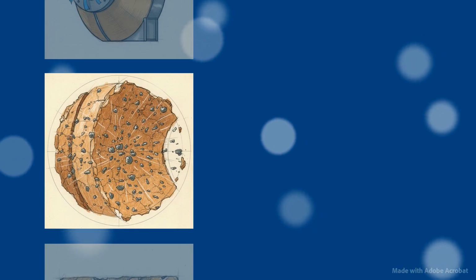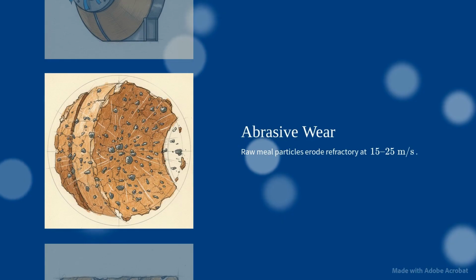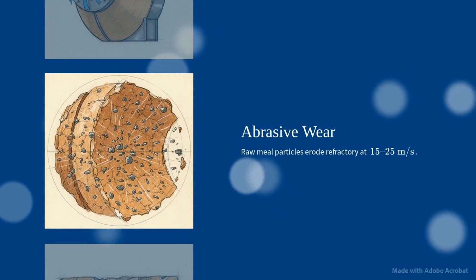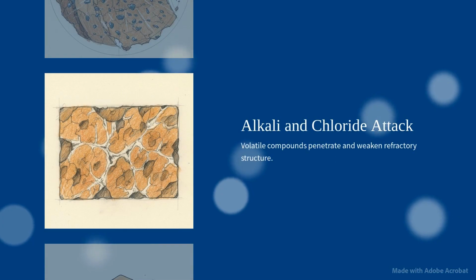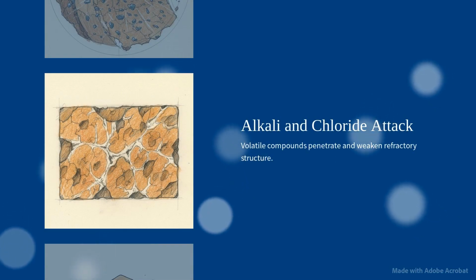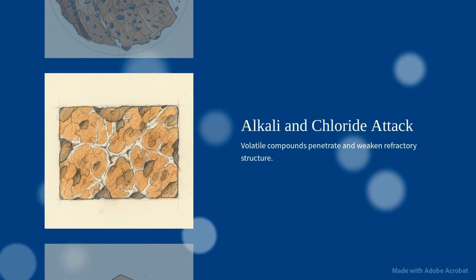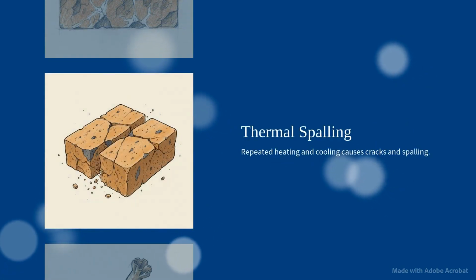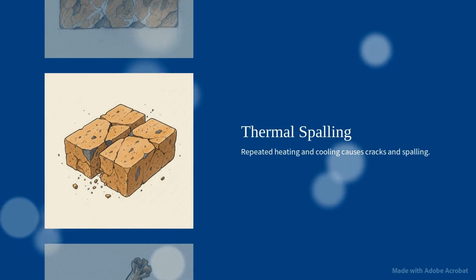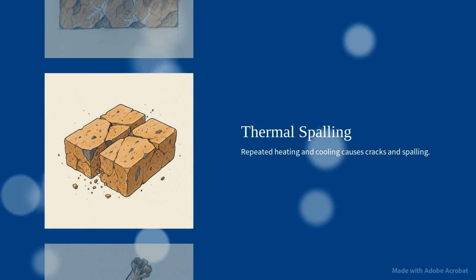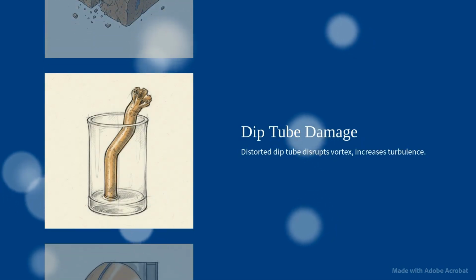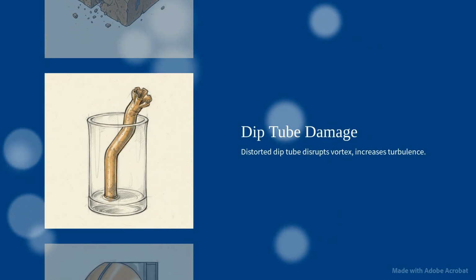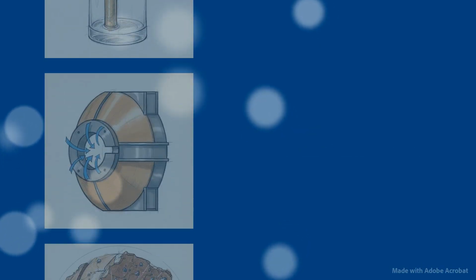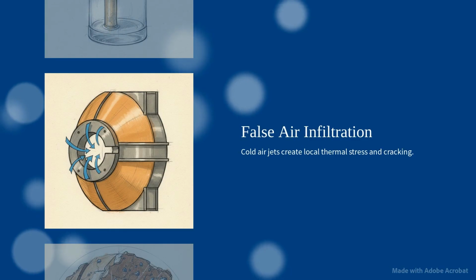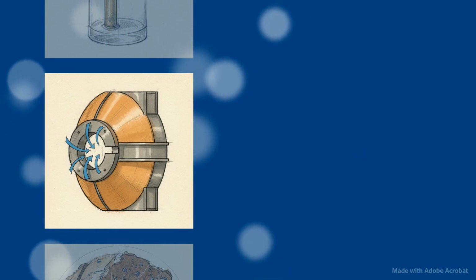Let's examine the main forces that lead to hotspots inside preheater cyclones. Abrasive wear happens as raw meal particles, moving at speeds between 15 and 25 meters per second, erode the refractory lining. Alkali and chloride attack occurs when volatile compounds like potassium oxide and sodium oxide penetrate and weaken the refractory from within. Thermal spalling is caused by repeated heating and cooling cycles, which create cracks and eventually lead to pieces of refractory breaking away. Dip tube damage, even a small deviation, can disrupt the cyclone's vortex and increase turbulence, reducing separation efficiency. False air infiltration introduces cold air jets that create local thermal stress and cracking in the refractory lining.